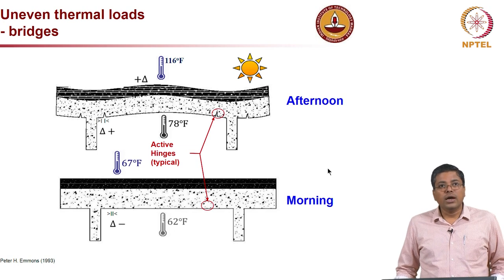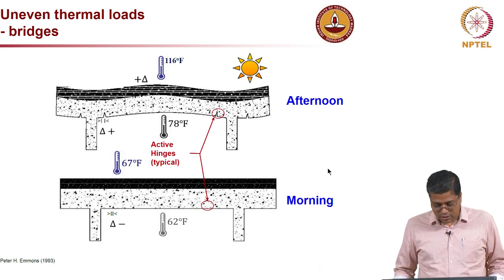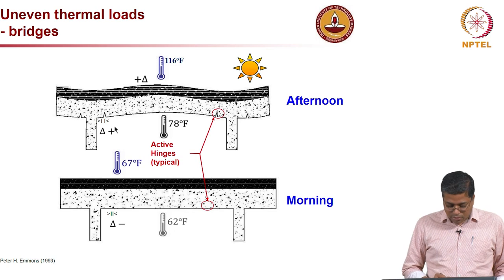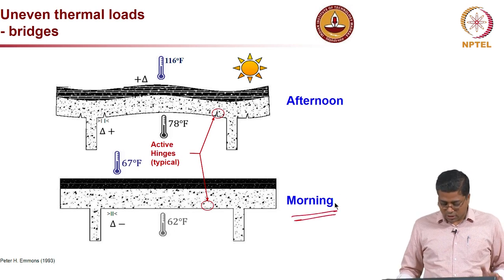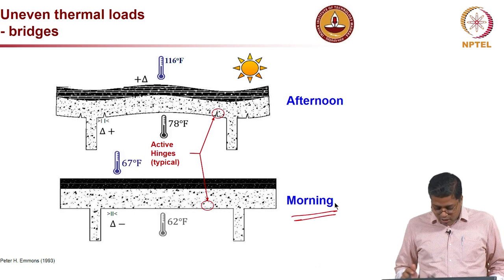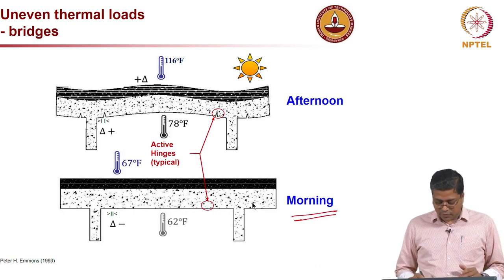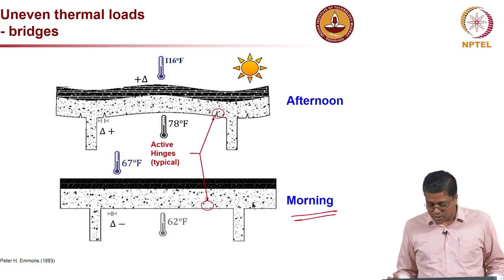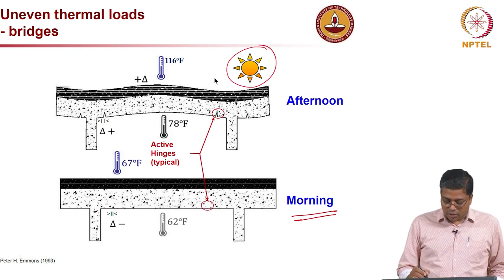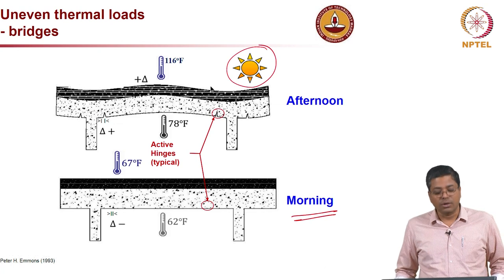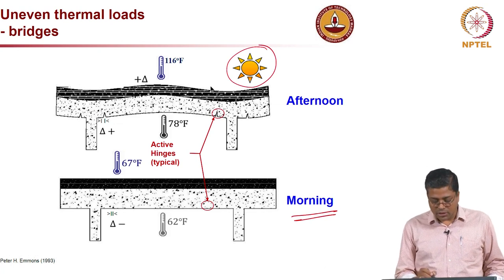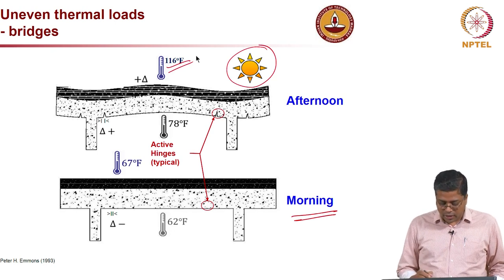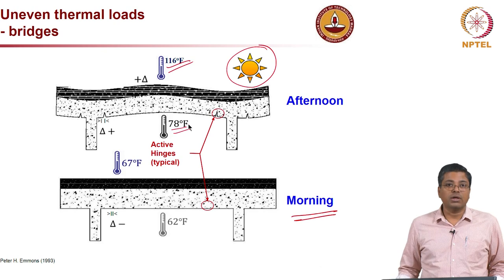Now, uneven thermal loads in bridge structures can actually lead to cracking, as you see in this picture. First look at the bottom portion of the picture, which indicates what the temperature conditions in the morning could be. The top surface and bottom surface, the entire bridge structure, could be experiencing similar temperature. But in the afternoon, if it is a really hot climate, the top surface of the concrete bridge might experience a higher temperature, something like more than 100 degrees Fahrenheit, whereas the bottom side could be at a lower temperature.